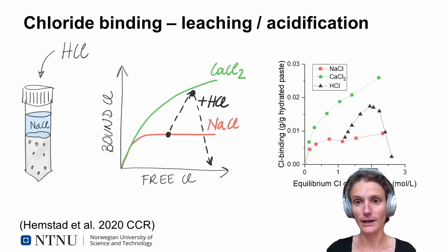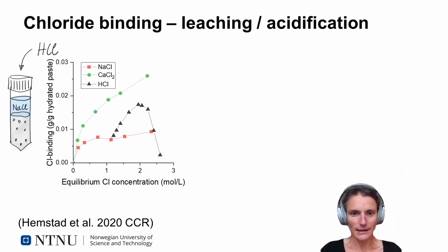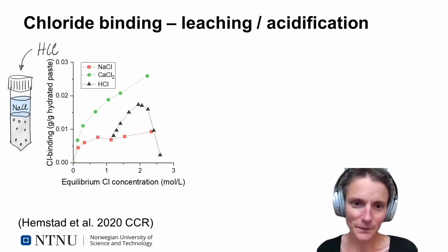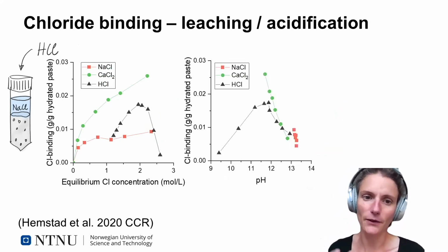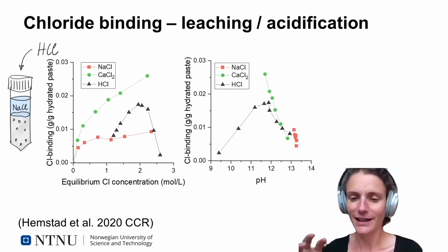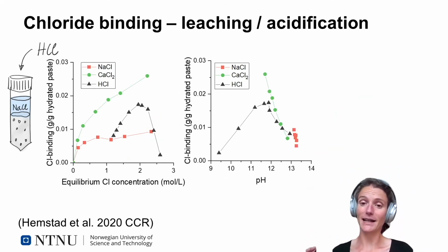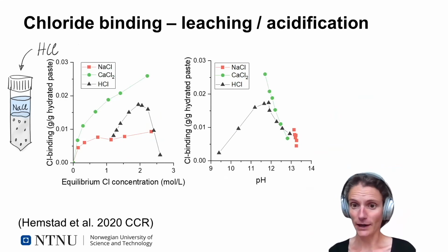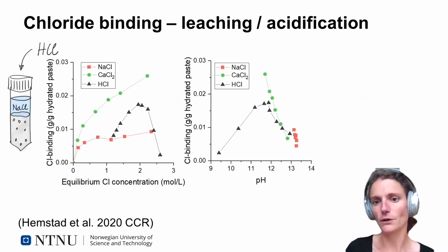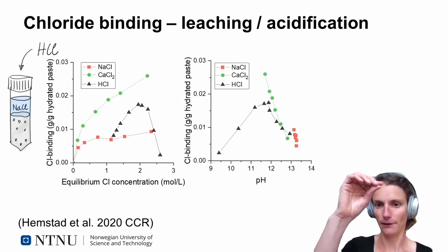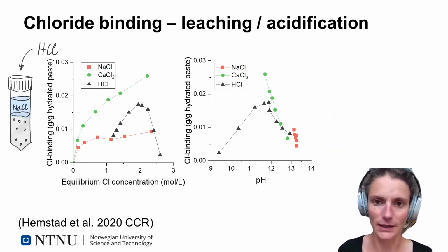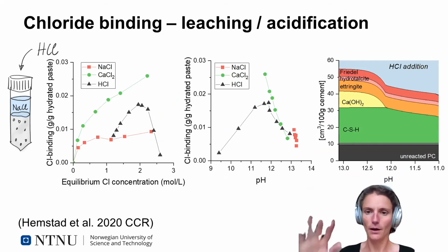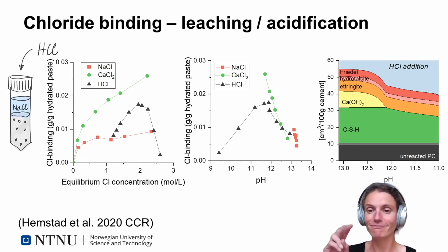So we see when we're adding hydrochloric acid, we first get an increase in chloride binding, and at a certain point, a decrease. So if we look at these experimental results, but we plot them slightly differently, we plot the amount of bound chlorides as a function of the pH instead of the chloride concentration. And what we see then is that when we start at a pH of 13.2 and we start to lower it, first the chloride binding increases until a certain level, pH around 12, and then it starts to decrease. This pH around approximately 12 is also the pH where we expect in the system that the portlandite will be dissolved. So then our system starts to become calcium deficient.